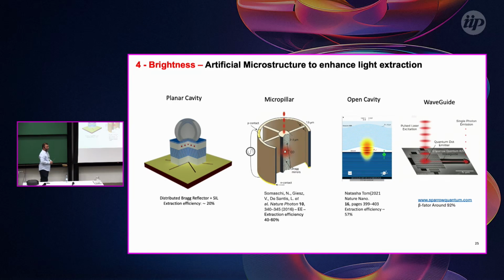But there are other groups, like the group of Quandela in France, that are selling single photon sources based on this kind of micropillars. And with this, they claim that they can get between 40 and 60% extraction efficiency. Another important result was done in 2021, again by the group of Richard Warburton, with this kind of open cavity. Basically, they grow DBR mirrors on the bottom of the sample. They grow the quantum dot sample, but for the top mirror, they use dielectric DBRs. They put the sample inside the cryostat, and they have a dielectric mirror that they can move and couple with the quantum dots. With this kind of approach, they reach almost 60% extraction efficiency.